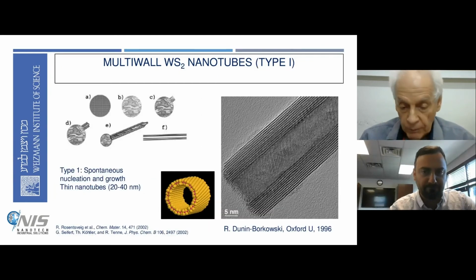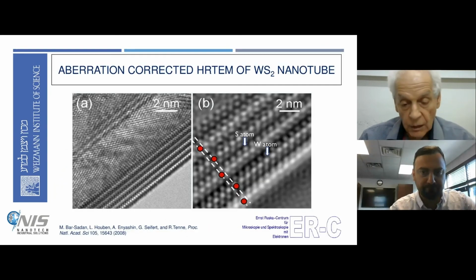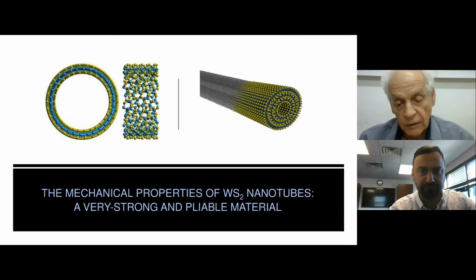We have to use surfactants. But I want to emphasize that the difference is that carbon nanotubes and graphene, and these nanotubes, do not stick very strongly to each other. Of course, they agglomerate - they will always agglomerate due to weak van der Waals interaction - but if you have 1 million nanoparticles and they stick together, they form an agglomerate of 10 microns or larger, and you can break them fairly easily, either mechanically with ultrasonic or with some other tricks.